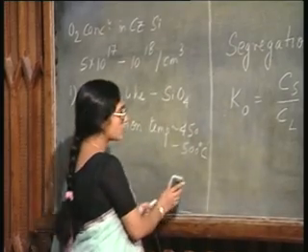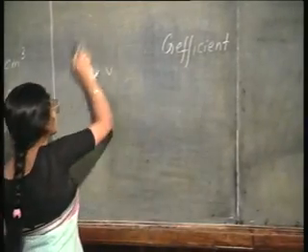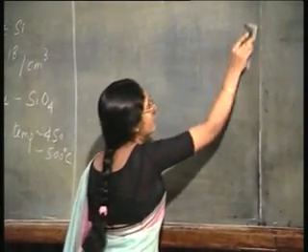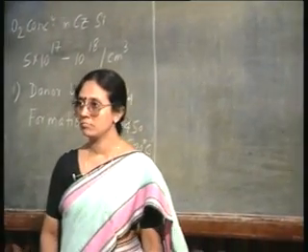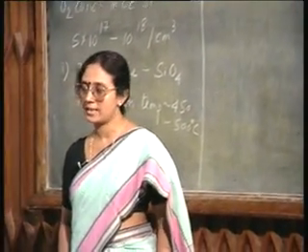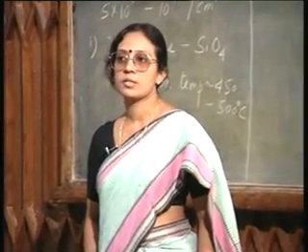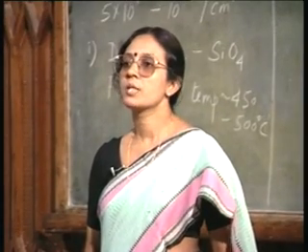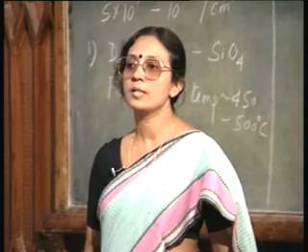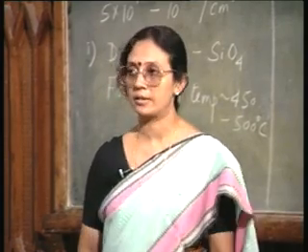Remember, this is only the 5% of oxygen that is not there in the interstitial site. 95% of the oxygen that is incorporated is in the interstitial sites. So, this oxygen in the interstitial site actually is, you could say, beneficial to silicon. It improves the mechanical properties of silicon, it improves its yield strength.